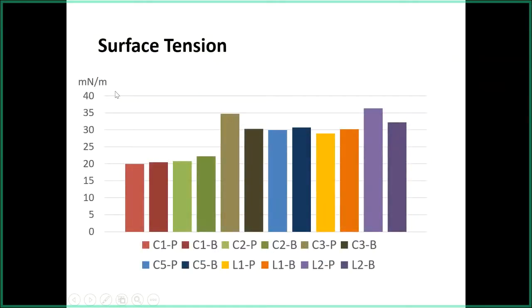Just want to point out the surface tension. This is the data I just showed you, but graphed. In each case, the two red ones are C1, petroleum and bio-based, and then C2, petroleum and bio-based. The structures that have issues are the ones that are the least soluble, and this is where you have the greatest sensitivity to surface tension. So I think there are really very minor differences in the polyether that we're picking up in this very demanding test.